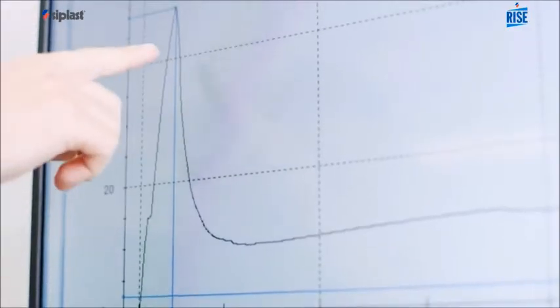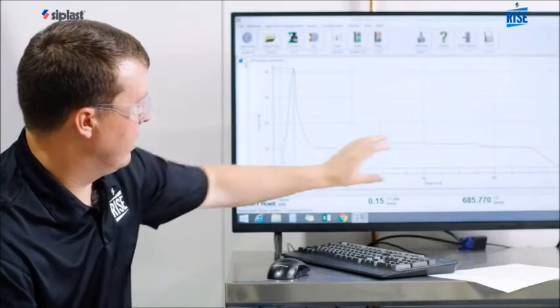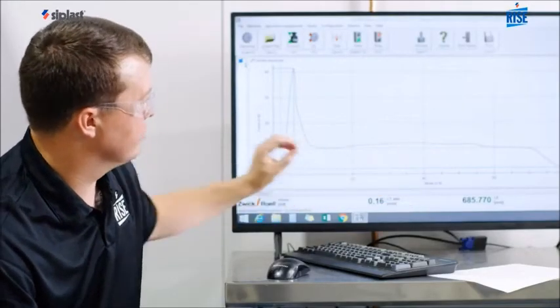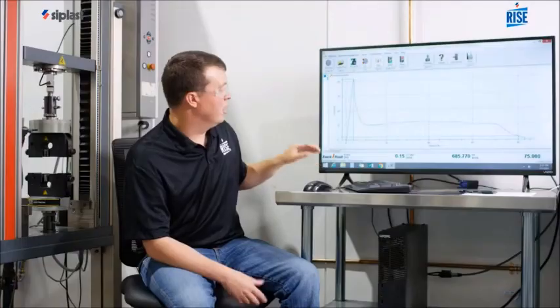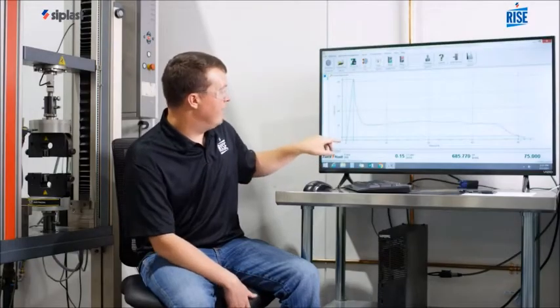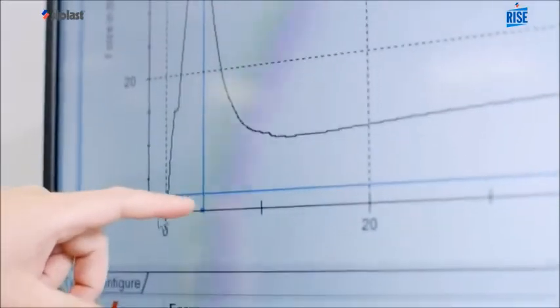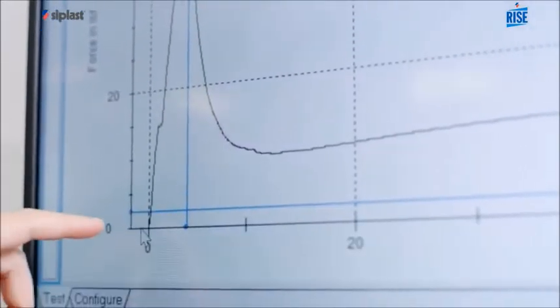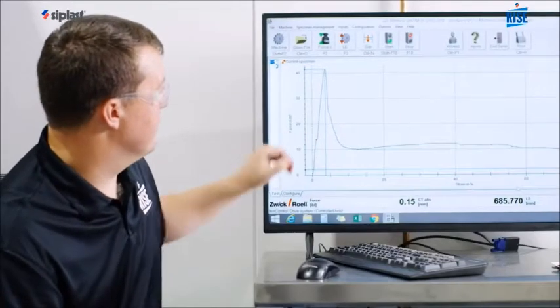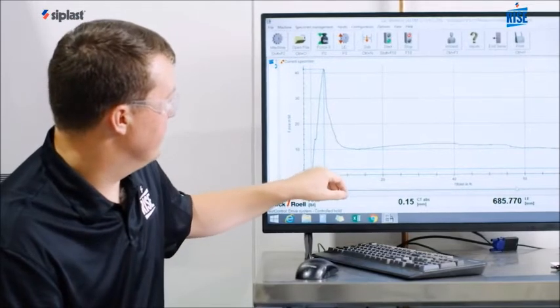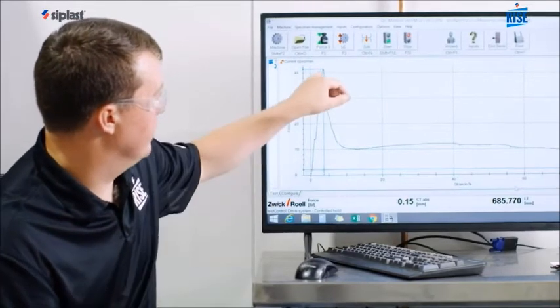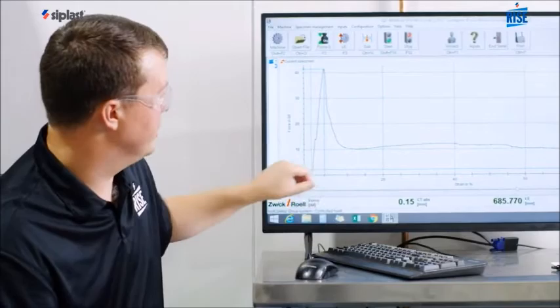That's where the fiberglass broke, and that's what we're seeing here as the peak load. And now the graph is starting to drop down. We're losing that load. What we're picking up now is the elongation, so this is our x-axis. Elongation at peak load is really what it says. It's the elongation that's reached, the stretch of that product. For this sample, it is the fiberglass. That's how far it stretched up until it reached that peak load. So there's your elongation at peak load.